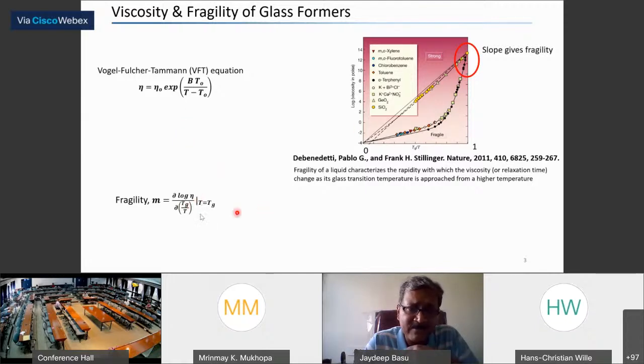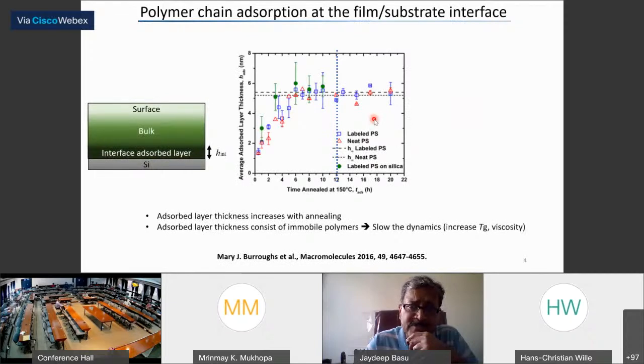The fragility is usually given by a mathematical form, but essentially you take a slope at this point approaching Tg, looking at temperatures in this regime, which are greater than Tg. So basically viscosity kind of diverges or goes to an extremely high value at or around Tg, and it jumps by several orders of magnitude. The other aspect that we will encounter here is the confinement effect, and I cannot go into the details of this field, which has been actively pursued for at least 3 decades. When one has a thin material which is really confined, then you start seeing deviation in many material properties. Here is one example where one is talking about the adsorbed layer.